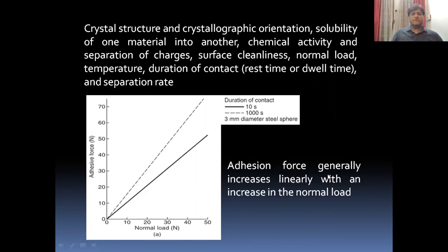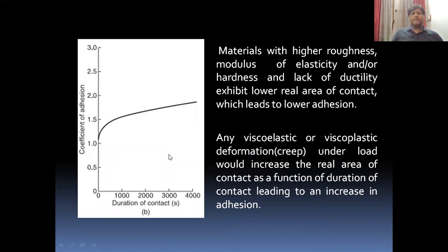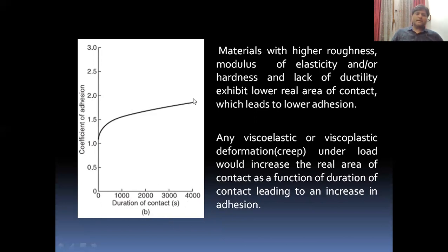The adhesive force generally increases linearly with increase in normal load, as seen from the graph. As you increase the normal load, the adhesive force increases, and this also increases with the duration of contact — shown by two lines for 10 seconds and 1000 seconds for a steel sphere of 3 mm diameter. Additionally, if a material has high roughness and high modulus of elasticity and lacks ductility, it exhibits a lower real area of contact and therefore lower adhesion. However, if there is plastic or viscoelastic deformation between two surfaces, that increases the real area of contact and the duration of contact, leading to an increase in adhesion.